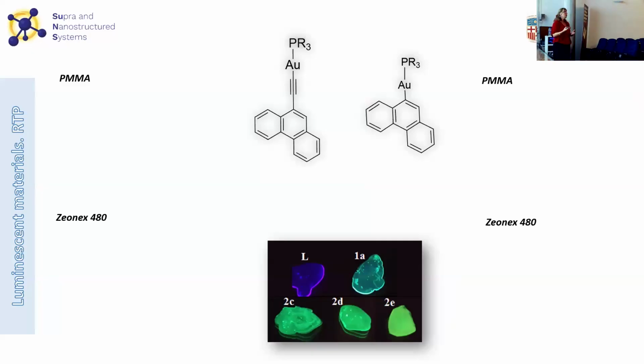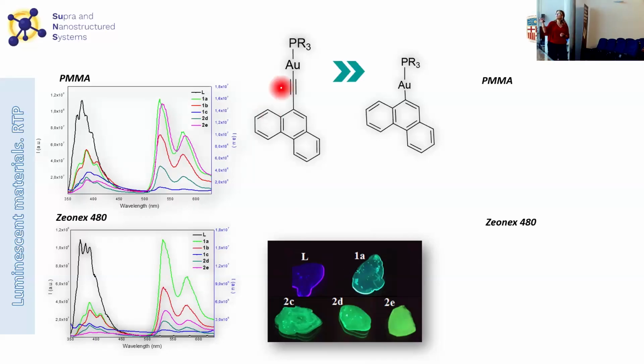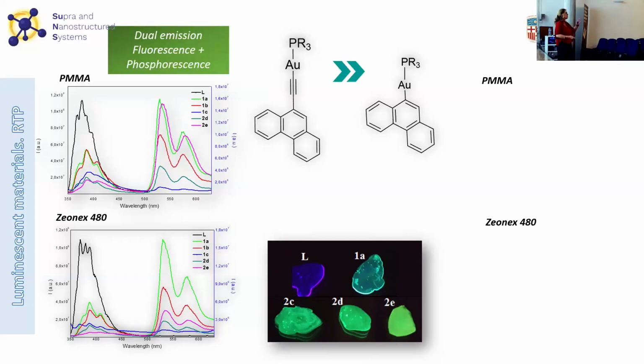We also performed these studies with two families of compounds, having the chromophore directly coordinated to the metal center, or just with a chromophore with an alkynyl bond in between the metal center and the chromophore. In these cases, we not only recorded the emission spectra in solution, but also in the solid state by the development of some materials with PMMA, polymethyl methacrylate, and Zeonex polymeric matrix. And we can observe that we can obtain these luminescent materials with the compounds. What are the differences between these two series of compounds? Well, in the first series of compounds, we can observe that there is fluorescence plus phosphorescence. So this is what is called dual emission, because we can have the emission coming from two places, the fluorescence and the phosphorescence.